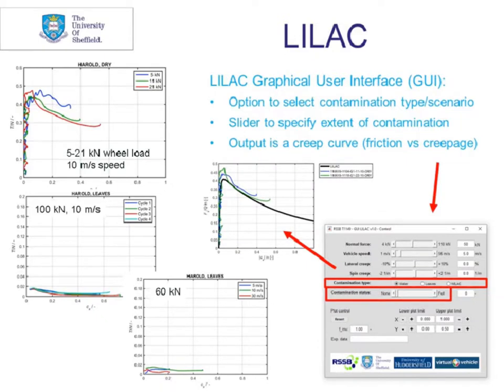So just to show you some typical output from the rig, the top left-hand graph is in dry conditions. So here we're up at about 0.4 for friction levels. And then when we start to apply leaves in these lower graphs on the left-hand side, you can see friction is almost completely consistently below 0.02. And that was for whatever load we applied and for whatever speed we ran at. So remember, these are representative speeds and loads for train operation. So very, very low friction.